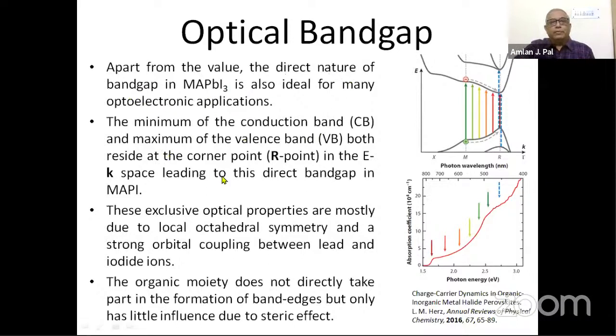So that means that, of course, I don't have to explain what a direct band gap semiconductor is. So you need very little of the methyl ammonium lead iodide material to absorb enough solar illumination. You will need only 200 to 300 nanometer thick material to absorb enough solar illumination, as compared to the 300 to 500 micron of silicon solar cell needed to absorb enough light. So that is the advantage, that the optical band gap is direct in nature. That is at the R point, so they are at the same point of the k-space, the conduction band minima and the valence band maxima.